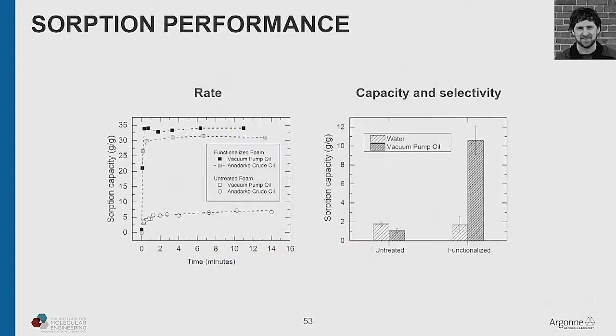And in the end, then you take it through to the next step with the silanization, and you get a pretty nice performing oil sorbent. So on the left here is shown how much capacity, grams of oil per gram of sponge over time. Now, if you start with just plain old polyurethane, it will absorb some oil, five or seven grams per gram, and it takes a few minutes to saturate.